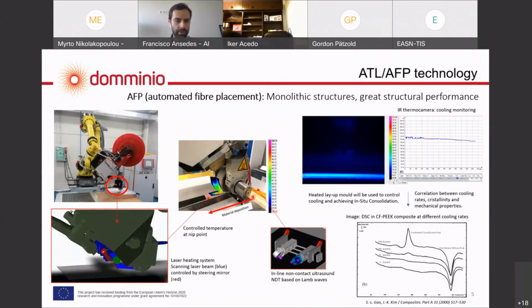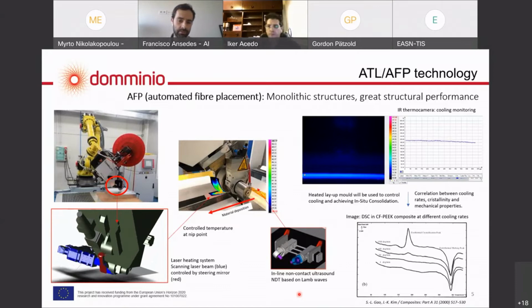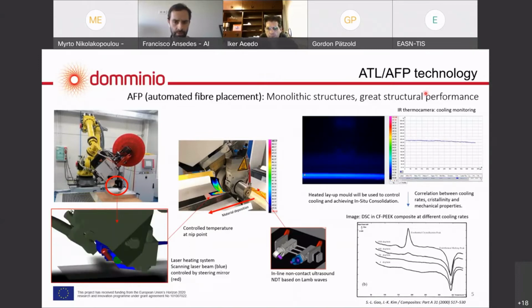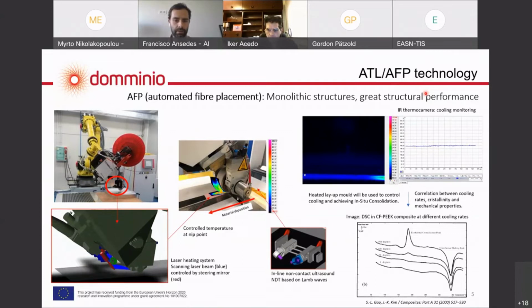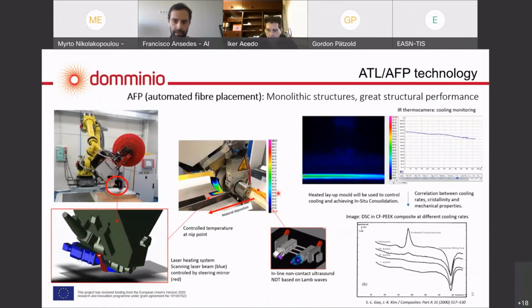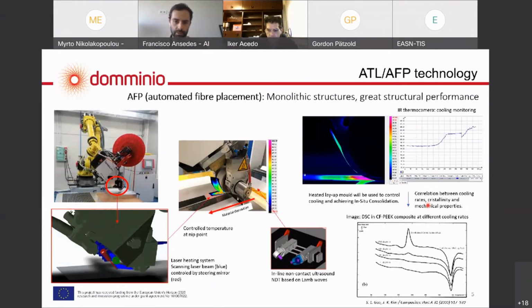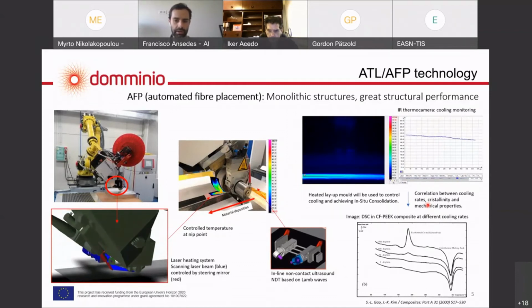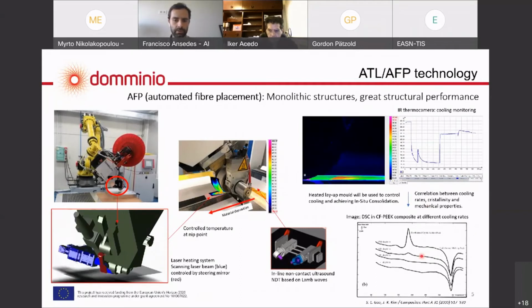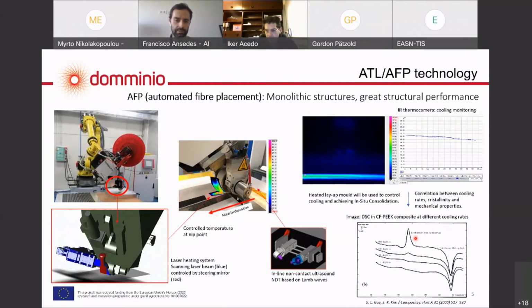Also for this project, we are developing a non-contact ultrasound NDT based on Lamb waves that will also be placed in the AFP head, so we have inline detection of defects. We are also doing thermographic imaging, infrared, for monitoring the temperature. You can see here an animation of the compaction roller passing and applying heat and the cooling down of the laminate, which we will monitor and obtain data from, to obtain the correlation between this cooling process and the crystallinity for each cooling rate. You can see here a picture of DSC crystallinity curves for different cooling rates, and we will correlate this with the mechanical properties.